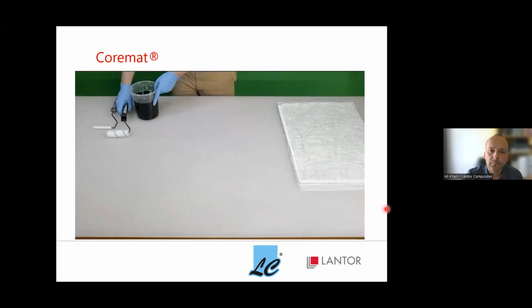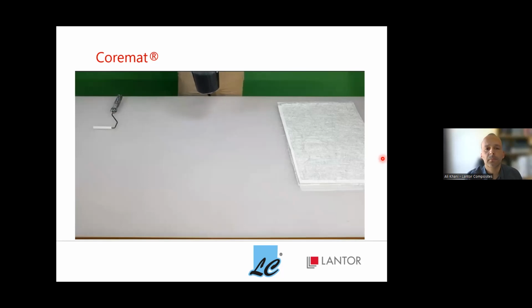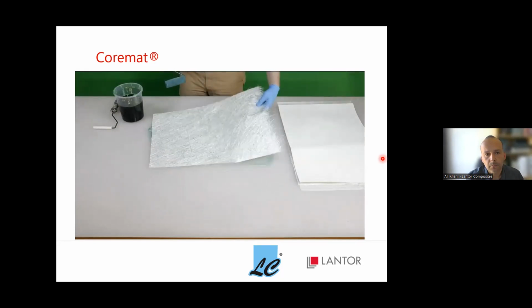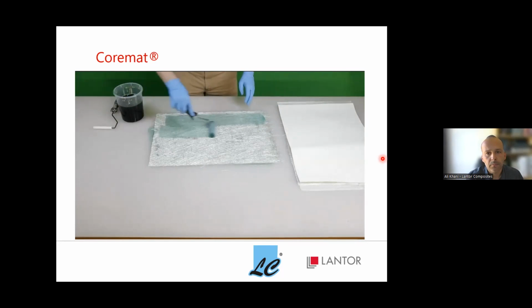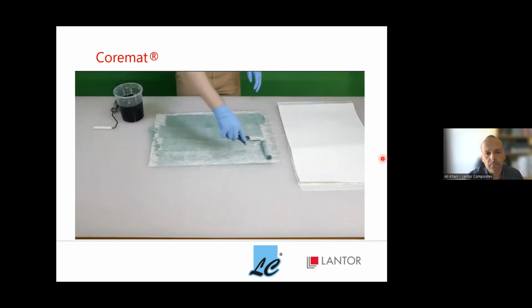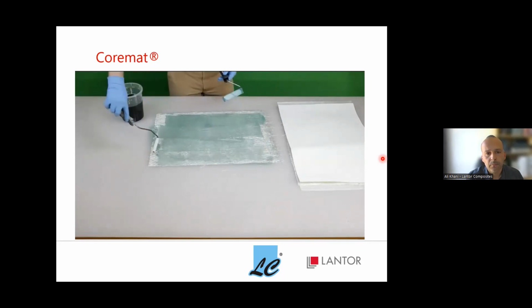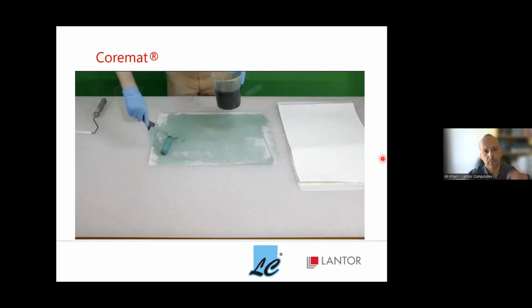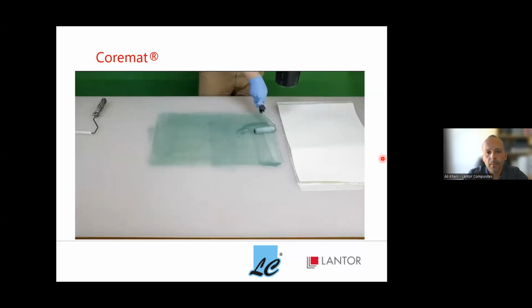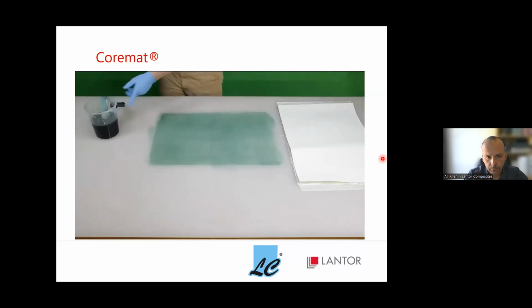Laminating with or without Coremat starts with applying a layer of resin to the mold surface. It is important to back wet fiber layers, which prevents air entrapment even after rolling the aeration roller. The first layer of glass is rolled thoroughly into the resin before adding more resin as required. We recommend to apply the core mat on a wet or slightly gelled glass layer to get an optimal bond between the core and the glass. We do not recommend to wait until it's fully cured. Should your project not allow this, we recommend to sand the laminate before applying the core mat, even if you've used a peel ply.